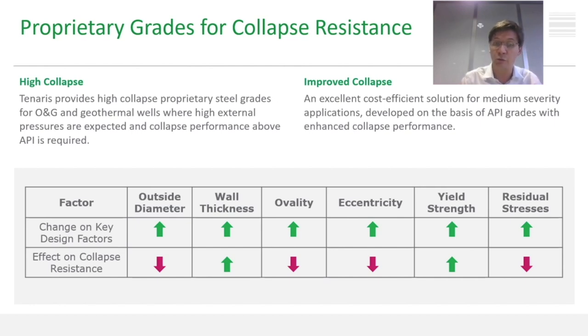We have a limit there, which is defined by the customer and by the need of a well design. Ovality is a parameter on which we can, through some specific quality control and some operative practice, reduce the ovality, and this will have a positive effect on collapse resistance. The same applies for eccentricity, which is the difference between the maximum and the minimum wall thickness on a section of a pipe. By controlling our pipe dimensionally in a better way, by increasing the quality control and improving our operation, we can reduce eccentricity and hence improve the performance in terms of collapse.